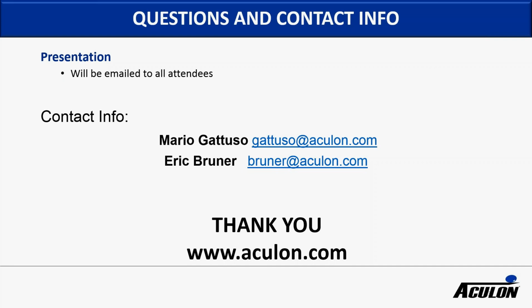In terms of bleach, that's going to be substrate dependent. A lot of metals will get etched by bleach, and generally anything that's going to etch the underlying substrate can destroy our coating, so I'd be a little bit wary of bleach. We can take a two-step approach to avoid some of that. We can do an epoxy plus a SAM to provide resistance to strong bases for some substrates. So I'd also encourage you to reach out to us with your application and see if we can help you.